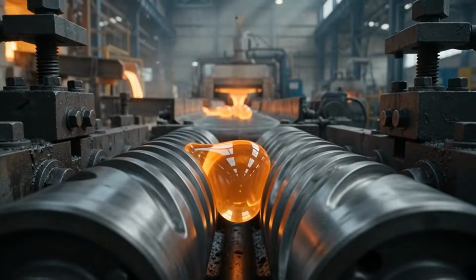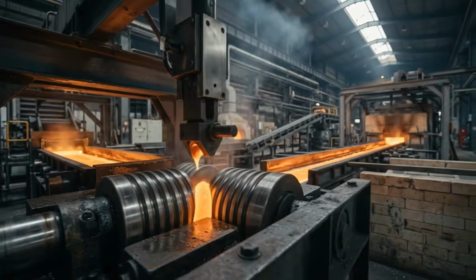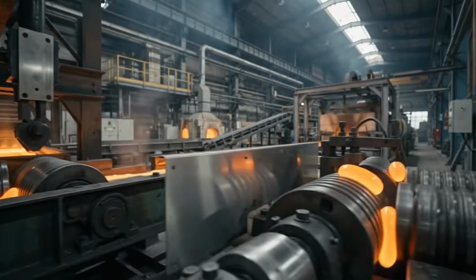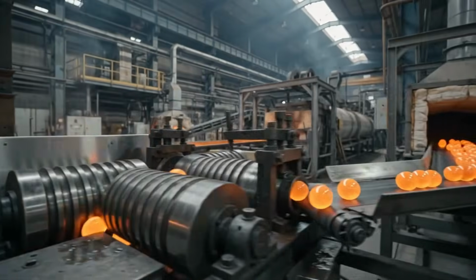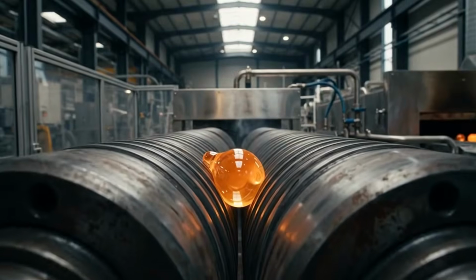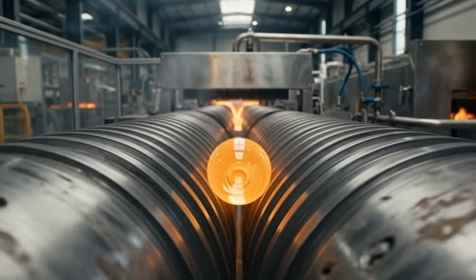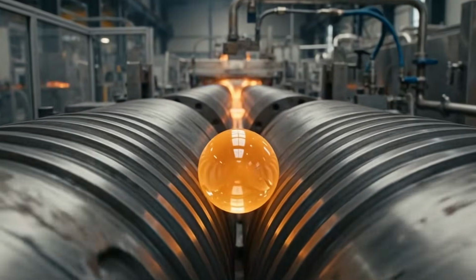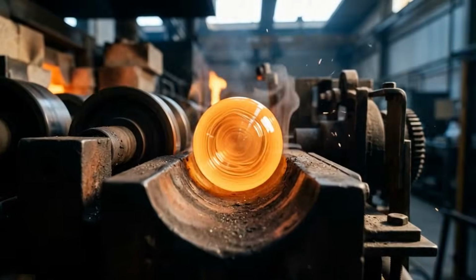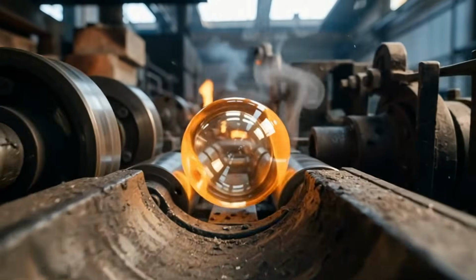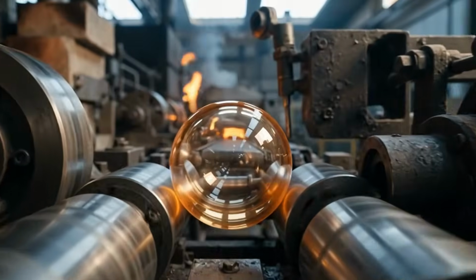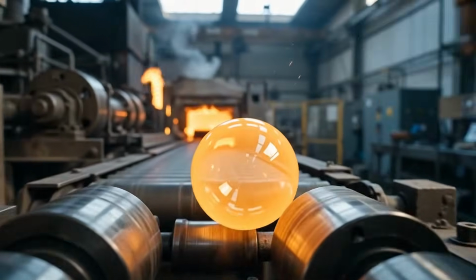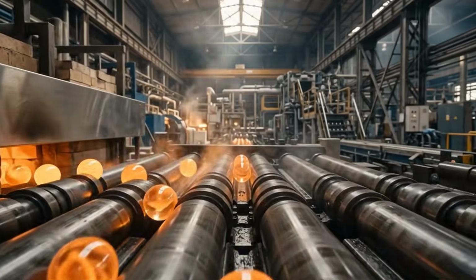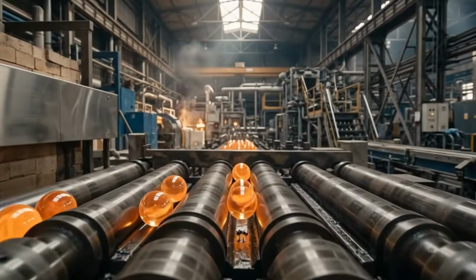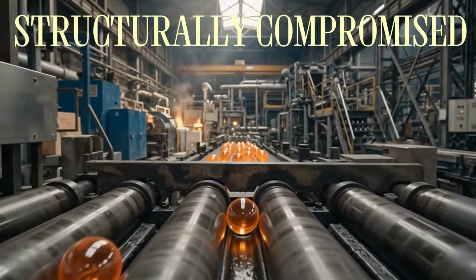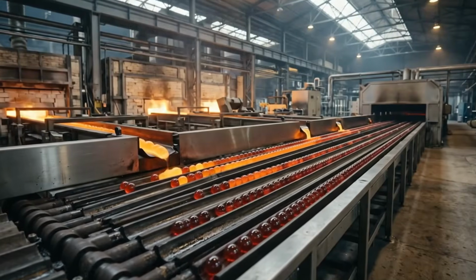Remember, I told you in the introduction that there's one step in this process that most people never hear about. The step that makes or breaks every marble ever produced. This is it. It's called annealing. After the marbles have rolled and cooled on the cast iron grooves, they're not finished, not even close. Because here's the problem. The outside of a marble cools faster than the inside, and when the outer layer hardens while the inner glass is still contracting, it creates internal stress. Invisible tension locked deep inside the glass. A marble with internal stress looks perfect on the outside, but it's structurally compromised. It can crack, split, or shatter from nothing more than a slight temperature change or a light impact.